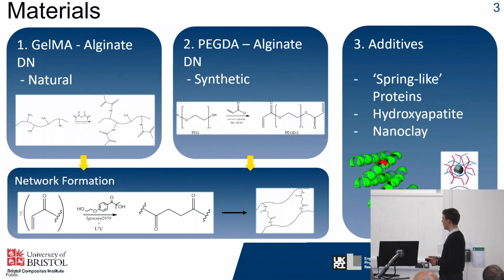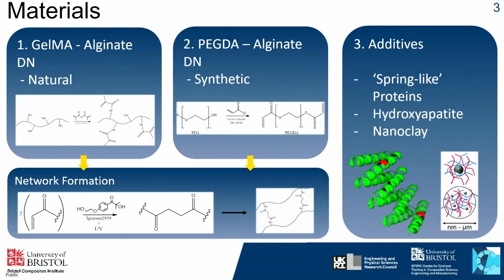And so the initial network formation is carried out using Irgacure 2959, which is a photo initiator, and that allows for the 3D network to form through a UV cross-linking reaction, which could then potentially be pushed through 3D printing to manufacture more rapidly. And then this 3D network is then submerged in the alginate solution, which forms a semi-interpenetrating network, which is then cured ionically.